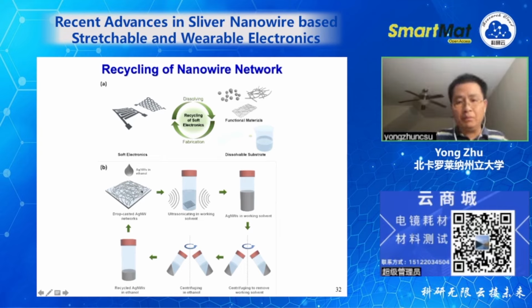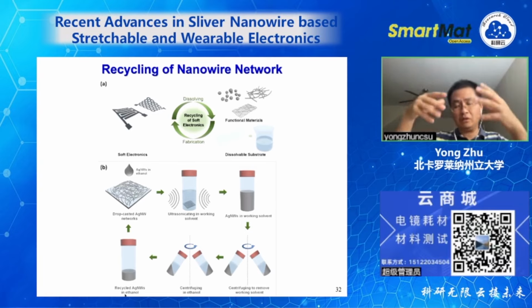Here is basically the same, but with a little more detail. Here we have a silver nanowire network. We ultrasonicate this in a working solvent to disperse the nanowire network into individual nanowires, and then we can centrifuge to remove, let's say, some particles or broken nanowires. Then we centrifuge again in ethanol. We always use ethanol as the last solvent, just to ensure that every time we drop cast, we have the same solvent. That's why we have this extra step. We put them in ethanol. So this is now the recycled silver nanowire in ethanol. It's basically the same thing as what we have originally: after synthesis, we have silver nanowires in ethanol. Now we recycle them also in ethanol.